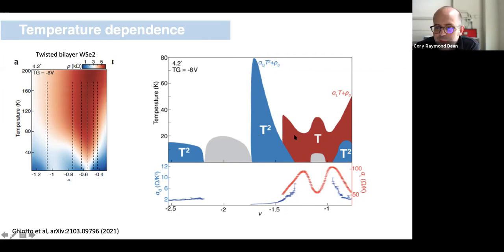Okay, so if you allow me for the moment, we're just going to discuss the low T behavior in terms of whether it's T-squared or T-linear. The other thing we can do is plot the coefficient of that behavior. So we call A0 here the coefficient of the T-squared behavior, and A_L the coefficient of the T-linear behavior. And what we see is that both of these peak at around a similar point. And we identify that point as evidence of the quantum critical point in the end.